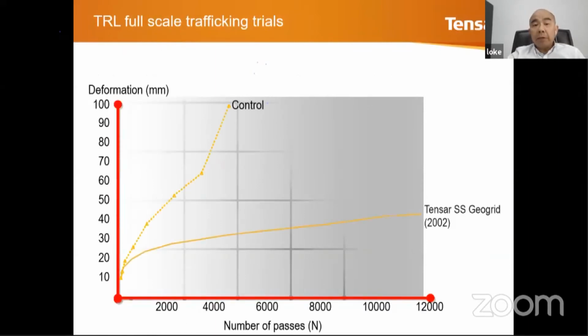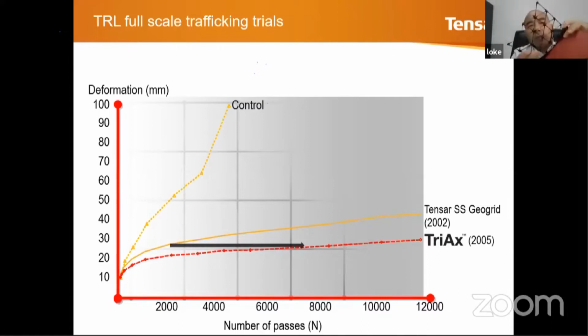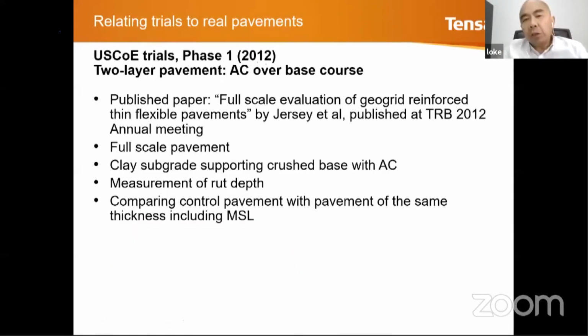Control, you can see that it failed very fast. Then you have got a square type of geogrid, which I showed you, which is not performing so well. And then you have got a triangular or a hexagonal shape of geogrid, and it performs much better. You can see that if you take a 25 millimeter settlement deformation, it performs about 6 to 8 times far better than the square geogrids. Okay, and this is the technology that we want to share with you in this presentation.